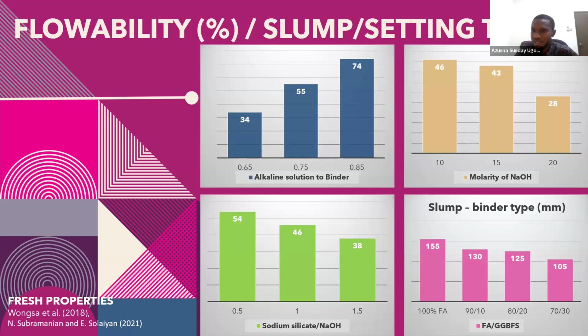Then the next thing is the molarity of the sodium hydroxide. So the molarity, like I said, starts from mostly 6 mole, 8 mole, 10 mole, 12, 14, 16, 18, and 20. But most times, if you're doing design of a geopolymer concrete, you're advised to limit your design to 8 mole and 14 mole most of the time, depending on when you get very advanced in the design. So if you look at the chart, you can see that the workability reduces with increase in molarity.